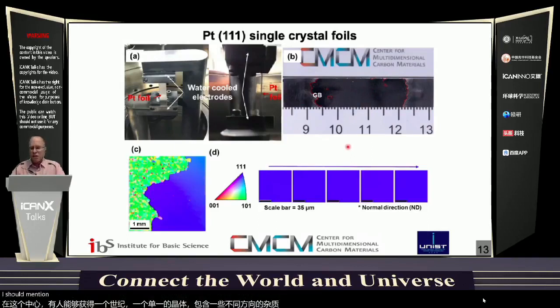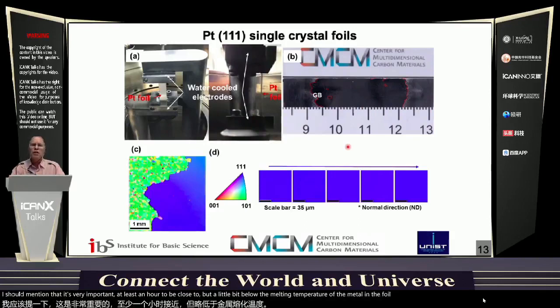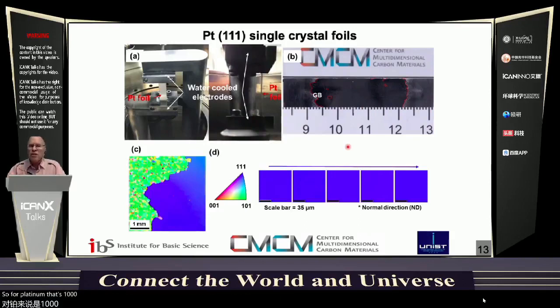I should mention that it's very important, at least in our work, to be close to, but a little bit below the melting temperature of the metal in the foil. So for platinum, that's 1,770 degrees C or so.